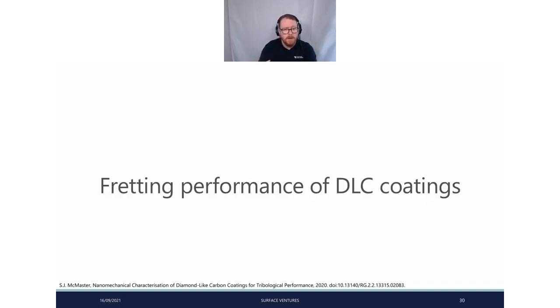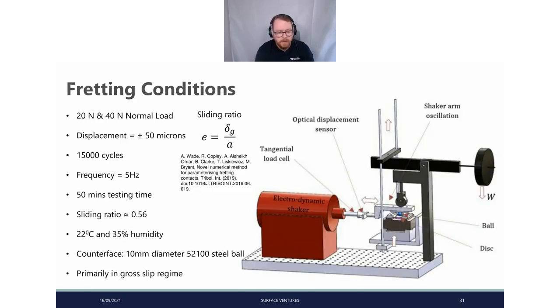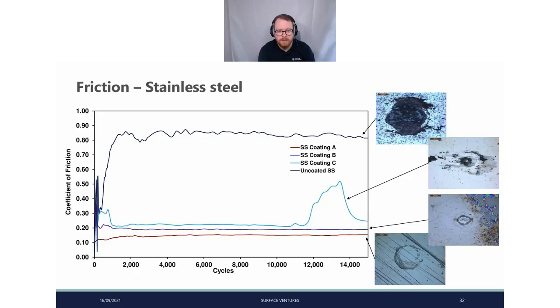I want to review quickly a little bit. So looking at time, I'll just move on quickly. So some fretting conditions here. So this is in gross slip, sliding ratio of 0.56. Typical lab conditions here. 10 millimeter diameter, 52100 steel ball. These are against various different types of DLCs. With a stainless steel substrate, we have our coating A, which is our amorphous hydrogenated. B is silicon doped. C is tungsten doped.